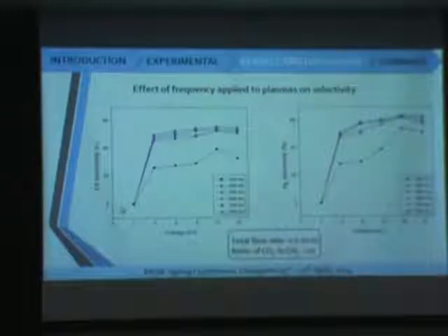And this figure shows the carbon monoxide selectivity and hydrogen selectivity. Here you can see that with the low voltage of 2 kV there is no reaction, but when we increase from 2 to 4, the selectivity increases very fast, and stays stable from 4 to 12 kV.